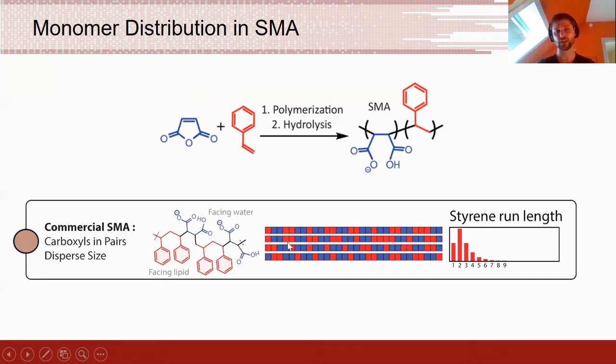And what you see is that, yes, of course, as the reactivity ratios prescribe, the maleic acid will never come 2 in a row, as in there'll never be 2 acid units in a row down here. But the styrene is pretty much all over the place. The average is around 2, so that's what you'd expect.